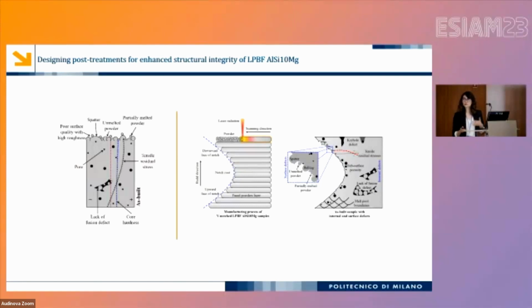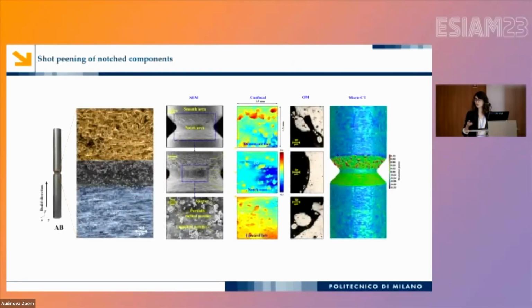Apart from the technology parameters, the geometry and the shape also affect the surface morphology, as we have variation in the angle of the surface with respect to the build direction. We see a lot of irregularities and variation in the distribution of local surface roughness in laser powder bed fusion. Here, for example, you can see a notched part that has very different surface features in the down-facing area, the notch root, and the up-facing area.